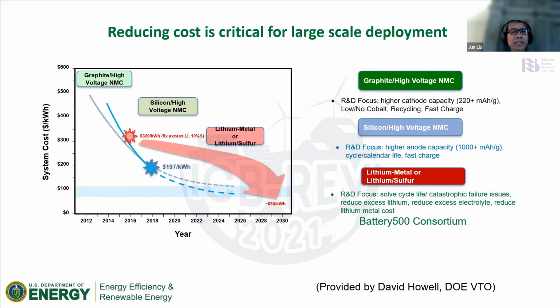So with that, this is the projection from DOE throughout the years. Today, the number is already much less than $200 per kilowatt hour, edging towards $100 per kilowatt hour. But in the next few years or 5 or so years, that number has to get to even less than $80 per kilowatt hour. And the option for that is to use lithium metal, as I said, with a high nickel NMC cathode material, or with lithium anode with a sulfur cathode.